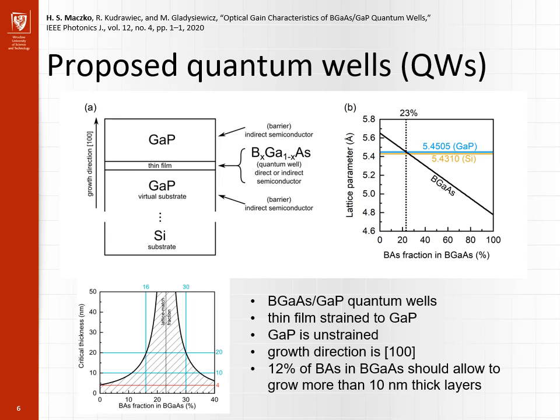Boron-gallium arsenide is a material strained to an unstrained gallium phosphide crystal. The alloy in general can be a direct or an indirect gap semiconductor, dependently on the boron arsenide fraction in the alloy. Whole structure is analyzed as grown along the 100 crystallographic direction of gallium phosphide, which has a specific impact on strain effects. Boron gallium arsenide is lattice matched to gallium phosphide at fraction of boron arsenide equal 23%, but already with 12% of boron arsenide, 10 nanometer wide layers of boron gallium arsenide should be possible to grow.